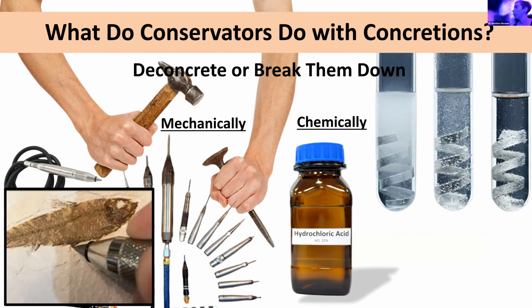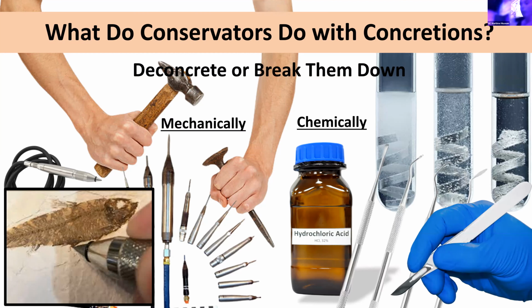We do still, in some circumstances, use acid digestion as a way to help soften up or remove concretion, particularly with materials like glass that are very fragile, or lead, which is very soft, in which the power tools might damage it in terms of gouging it or breaking it. In which case we'll, in a very targeted way, introduce a very dilute form of acid, for a very short period of time in very specific locations to soften up that concretion, after which we can go after that area again with hand tools like scalpels and dental picks to then remove the artifact from inside.